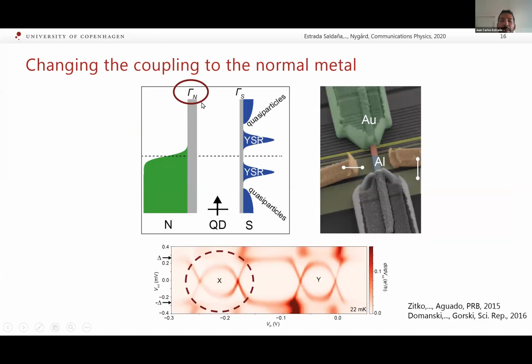Next, we studied the coupling of the quantum dot to the normal metal. So we wanted to increase it to see if there is some kind of Kondo effect appearing, because we increase the coupling of the spin to the normal metal, and there should be some screening happening. And we do this by changing the voltage on this local gate, which is closer to the normal lead. And we do this study on the left loop.